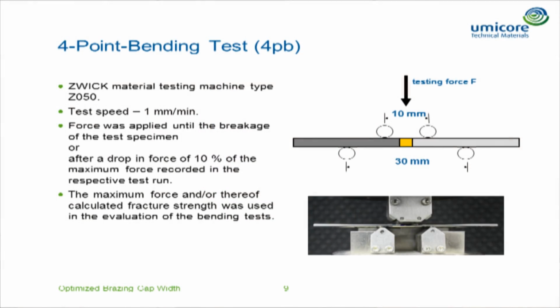After these parts were brazed and ground, we made the 4-point bending test. Here you can see how the test specimen was placed in between. We used ZWICK testing equipment, and the speed was 1 millimeter per minute. We stopped the test after the part broke, or after we got a drop of 10% of the maximum force we applied to the part.